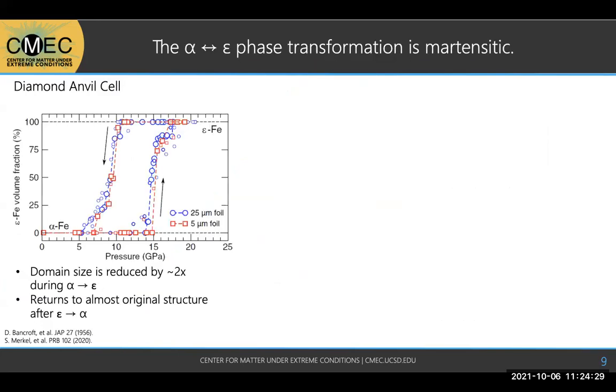Next slide. Thanks. So this phase transition is martensitic, which is really important for us. It means that it occurs rapidly through the shifting of atomic planes. This is in contrast to diffusion-based transformation, where the atoms slowly migrate across an interface or something. Martensitic transformations happen pretty much immediately.